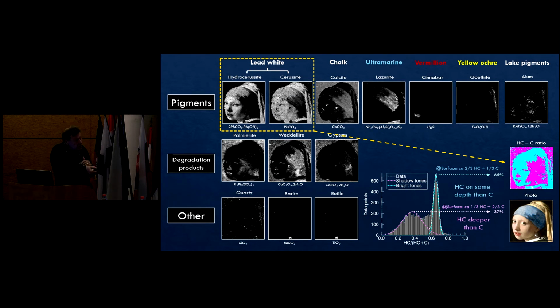So we figured out that actually here, when you look at what is bright blue, so the light parts, there is nothing special going on. The one component, this lead carbonate, is more or less on the same average depth below the surface as the other component, so that's okay. But here in the shadow parts, they're different. There is a distinction in depth. So we feel this, but we cannot really touch that in a very quantitative way.